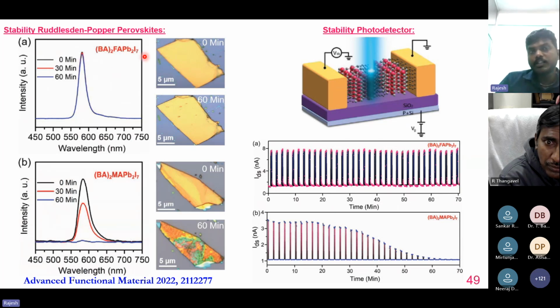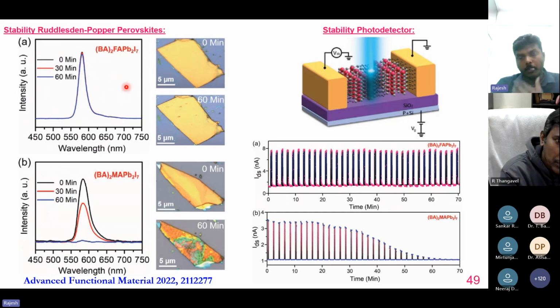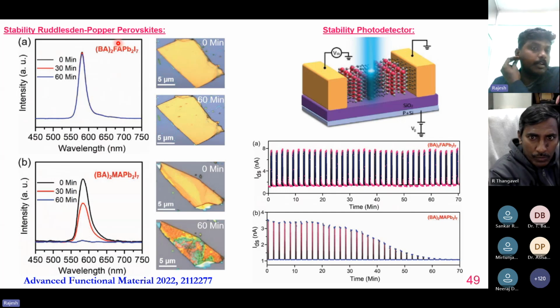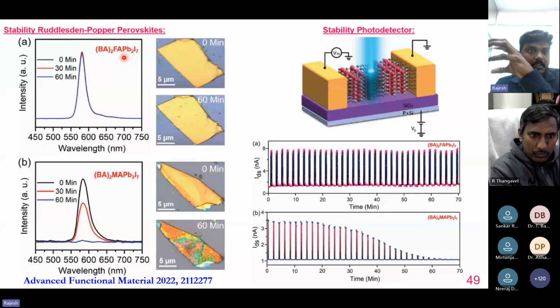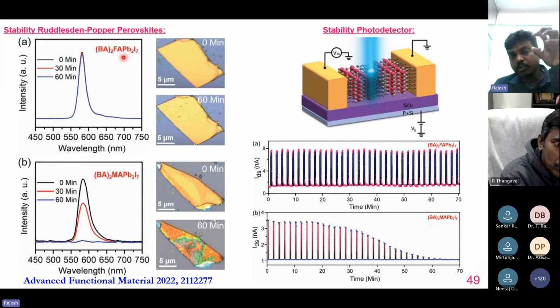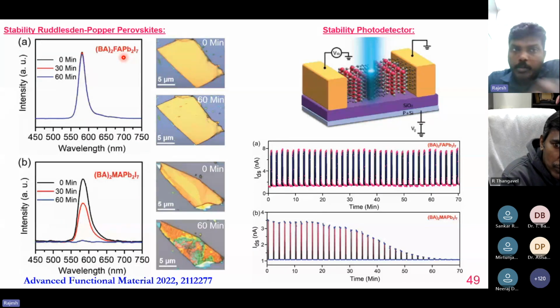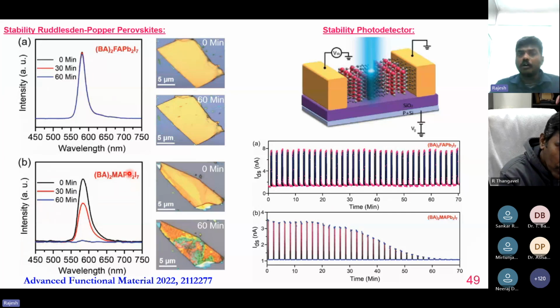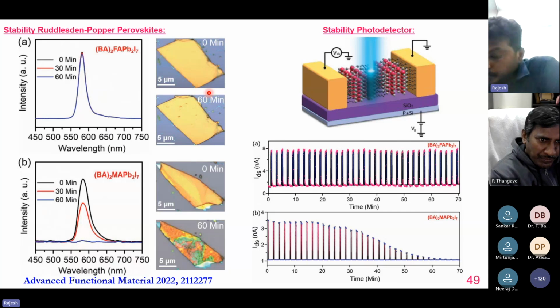Why is this formamidinium based so much more stable compared to methylammonium? Here the size plays a major role, because the size of the formamidinium ion is very large. This large size is able to strongly incorporate into the perovskite structure. So the movement of ions will be less compared to methylammonium, because its size is small. The migration of ions is high in the methylammonium structure compared to the FA based structure. In this way, we are able to improve the performance of the material.